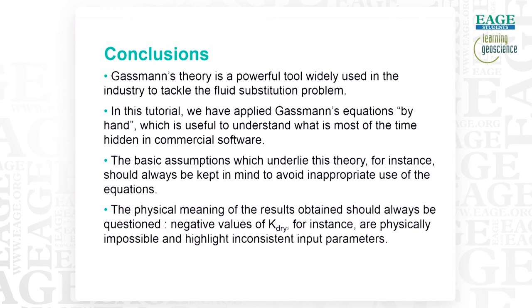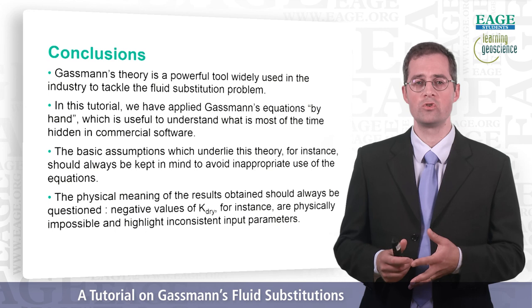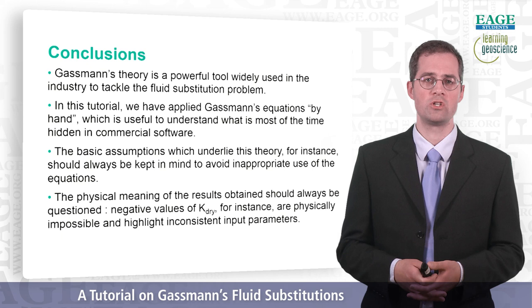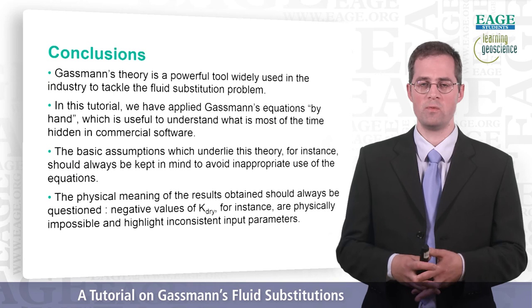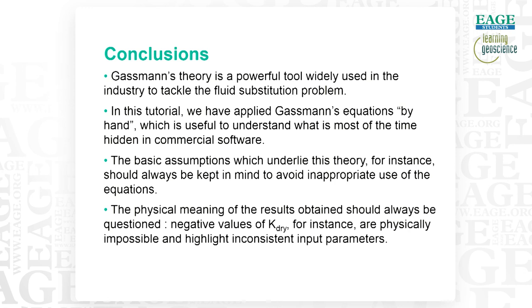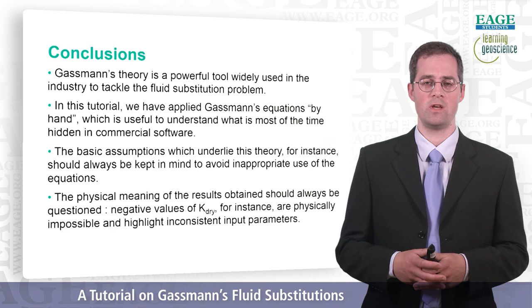And last but not least, you should always be very critical with the results you have. For instance, K-dry is something which is physical, so you shouldn't have negative values. It cannot exist. If you have negative values in your K-dry computation, it means that somewhere in your computation you have a mistake, maybe due to saturation, porosity, or your K mineral, which is not correct. But anyway, you have to check your input parameters to make sure that the K-dry you get in the end is positive. This was a pleasure to go through this Gassmann tutorial with you.